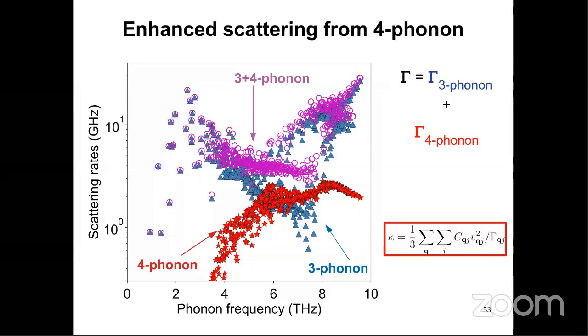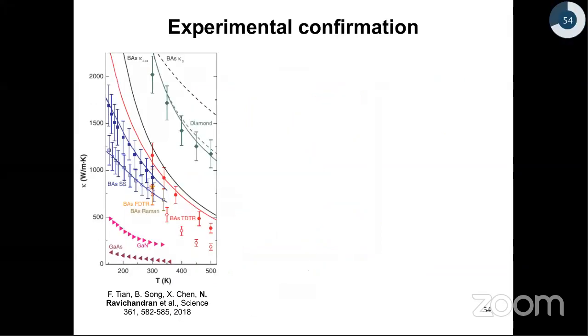Okay, so these are just computations, right? So how do we know these things are actually happening in reality? So to confirm that, we collaborated with our experimental colleagues who fabricated, actually grew these crystals of boron arsenide for the first time in a very pristine manner with very few defects. And they were actually able to confirm our theoretical prediction.